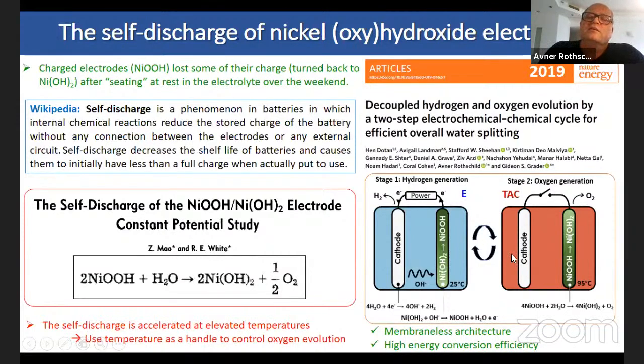Then you change the electrolyte in the cell from cold electrolyte to hot electrolyte, and the hot electrolyte induces this spontaneous reaction with water that emits oxygen, completes the water splitting cycle, and regenerates the electrode back to its original state, and then you can cycle this again and again and again.